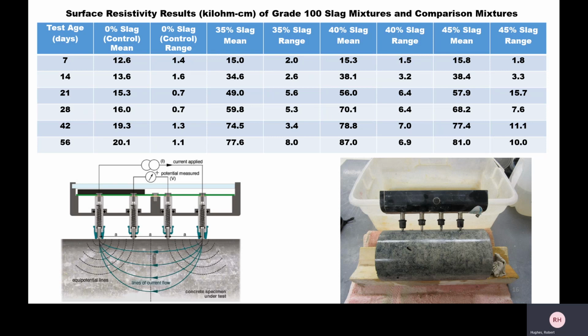Now our SR results, which, like I said, is the measurement of permeability. And here we have a column for each, the mean SR and the range. For our SR, we use these Resipod Proceq, the 38 millimeter, I believe, that puts a charge from the external probes through the 4x8 cylinder, and the middle probes will measure the potential in between it. So a higher SR value is better because that points to more surface resistivity and less permeability.